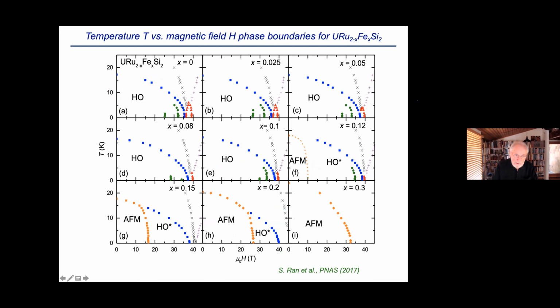So this is the hidden order phase boundary. This is a phase that occurs in the hidden order regime where it's believed there's some Fermi surface reconstruction. This is this exotic phase, which envelops a quantum critical point that's believed to be in this region right here. And so this is where you have the itinerant, highly coherent region over here, the heavy fermion state, if you like.